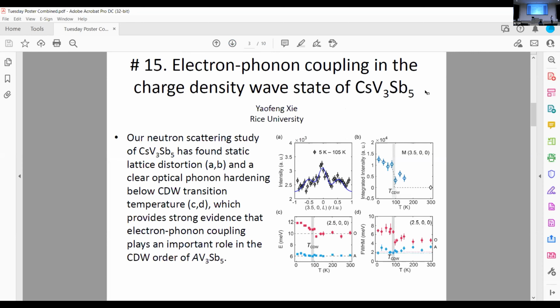Yeah, so our work is basically using neutron scattering to study how the lattice is involved in the recently discovered vanadium-based kagome superconductors, the 135. Using elastic neutron scattering, we have found the static lattice distortion corresponding to the 2x2 superlattice below the CDW transition temperature. And also, using inelastic neutron scattering, we have found a pronounced phonon hardening at the CDW wave vector below the CDW transition temperature. So, in contrast to the previously proposed purely electronic origin of the CDW order, our results suggest that the electron-phonon coupling plays an important role in the CDW order of the 135 family.